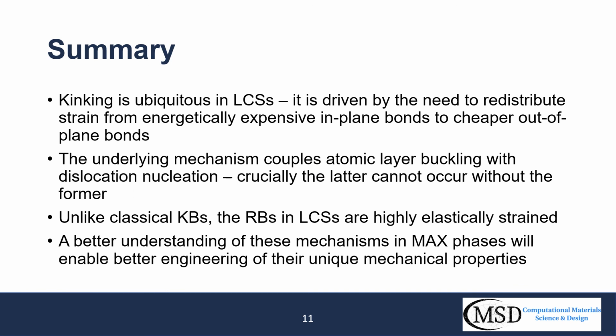So now to wrap up, I'd like to present a few summary points. Kinking is ubiquitous in layered crystalline solids and is driven by the need to redistribute strain from energetically expensive in-plane bonds to cheaper out-of-plane bonds. The underlying mechanism couples atomic layer buckling with the nucleation of dislocation dipoles. It's important to note that these cannot be separated. The latter cannot occur without the former.